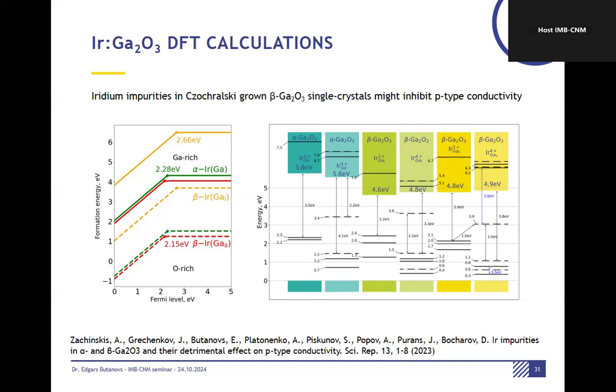What we discovered is that it inhibits p-type conductivity. If you want to obtain n-type, there are also some not-so-nice defects. Takeaway: you shouldn't really grow device grade beta gallium oxide from Czochralski. Nowadays, I think they do the floating zone method, so that's already not that relevant, I guess, but there are some nice theoretical results from that. Okay, I think that was quite quick.